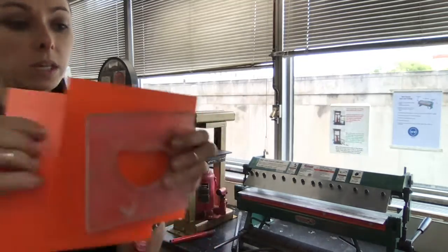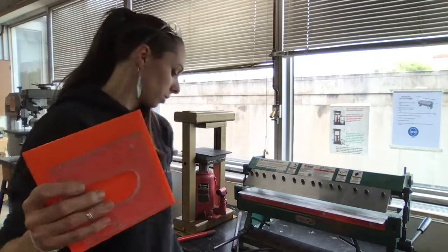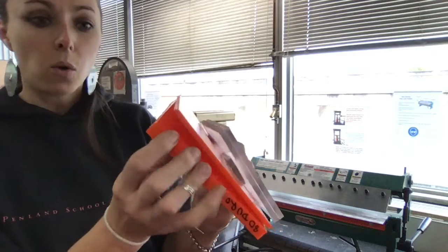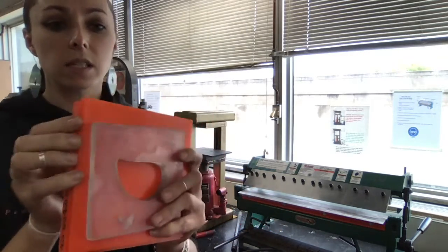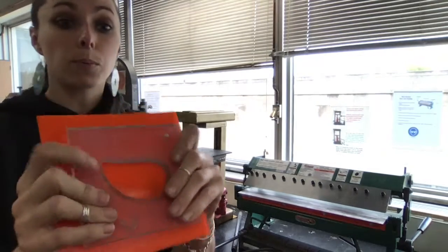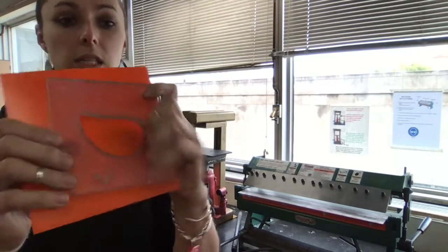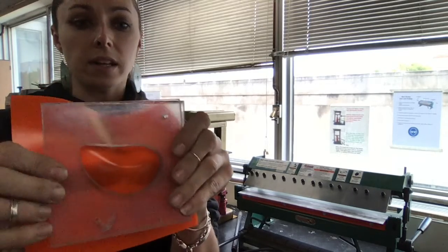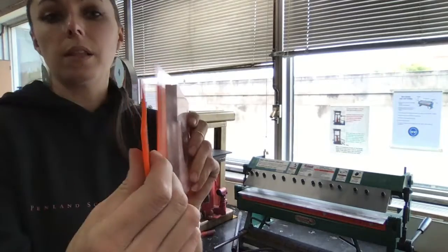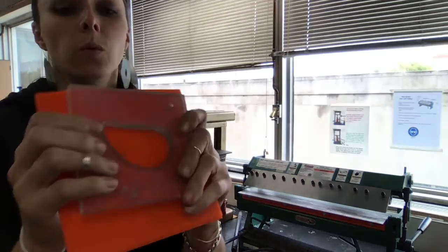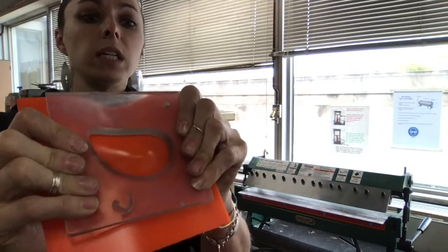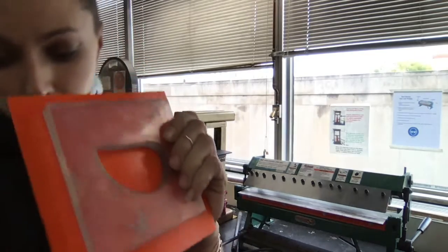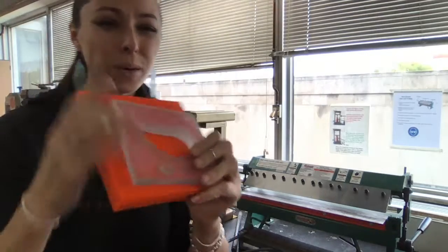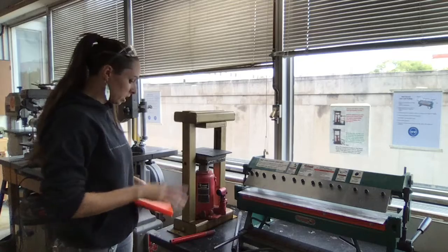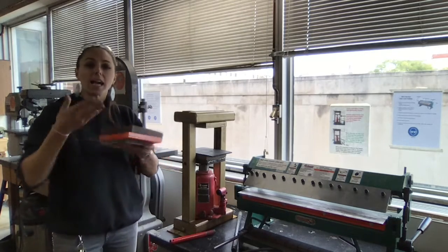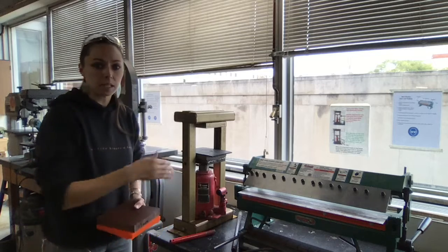And the reason we want to add as many support structures, like these three layers of 80 durometer in here, is because the more support you have, the more even the pressure is. So if I just use this thin one, it would go in and it starts to buckle. If I use the 1/16 of an inch and 1/8 inch with my die, it starts to push it in really evenly. And with all of that pressure, we want to support it as much as possible, and we don't want to max out the ram. So we want to add some additional material to give us more height so that we're not maxing this ram out inside of this bottle jack.